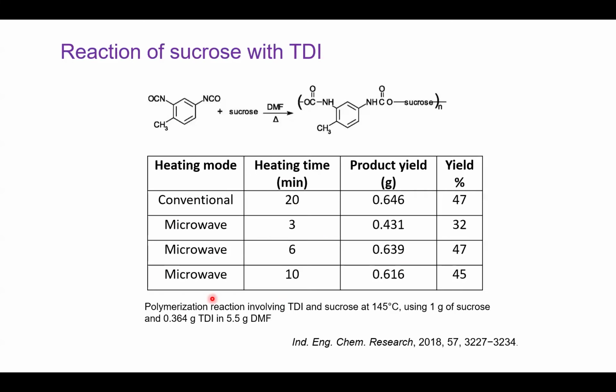So here is the reaction, a very simple reaction, almost a green reaction. We just take the TDI and just heat, and then you can generate this polymer. And we did it with both conventional heat as well as microwave. So here's conventional heat, 20 minutes; microwave, actually 6 minutes; you get the same yield. So here is a way, again, of a greener process. Using microwave, you can save energy or save time in terms of the reaction, and you get the same product.